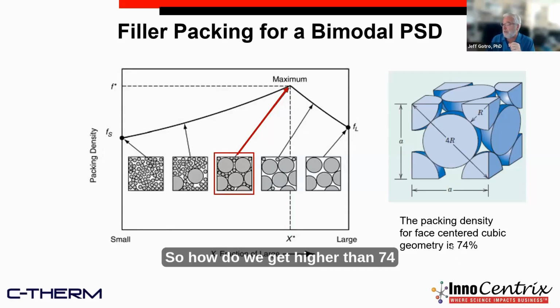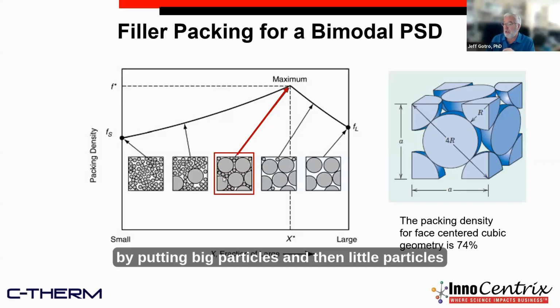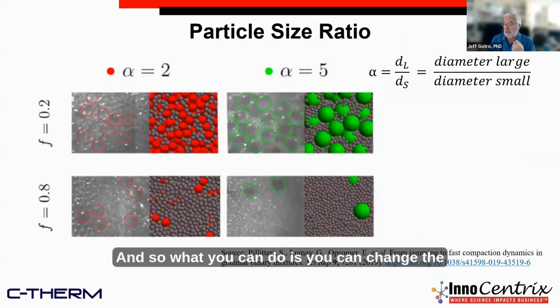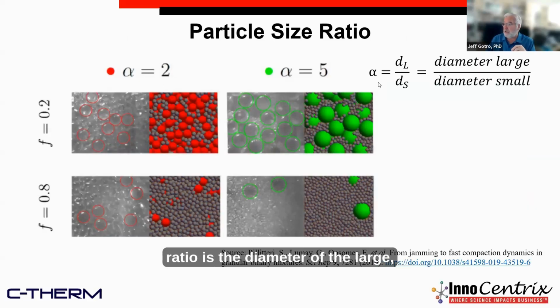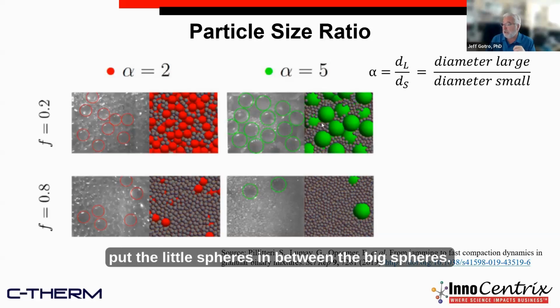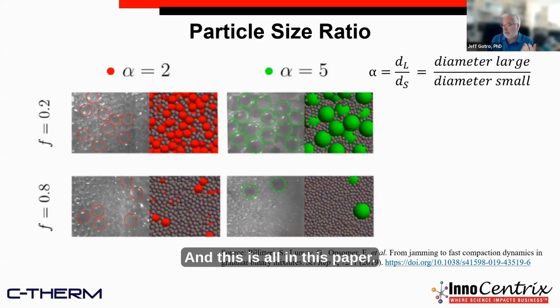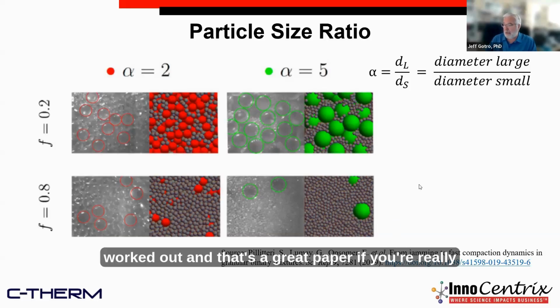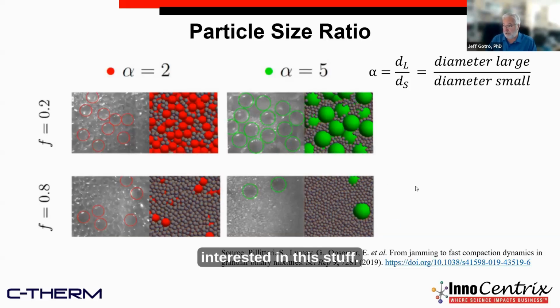So how do we get higher than 74% filler loading? We go through this bimodal distribution. We can get to this maximum by putting in big particles and then little particles in between. What you can do is change the ratio of the diameter of the large to the diameter of the small, and come up with different ways to put the little spheres in between the big spheres. This is all in this paper, where all this stuff has been worked out, and it's a great paper if you're really interested in this stuff.